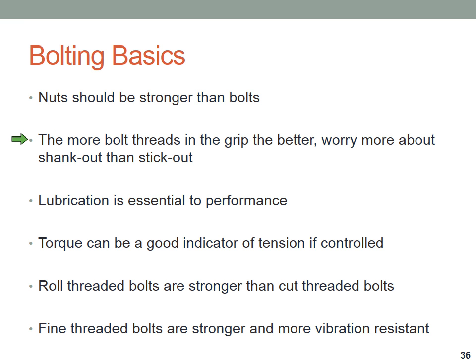Generally speaking, the more bolt threads there are in the grip, the better. Bolts are essentially very stiff springs. Most of the stretch that occurs in a bolt when it's under high tension is in the area of the highest stress, or the smallest diameter, which is in the threads. As a bolt is tensioned, most of that stretch is happening in the threads. If you haven't left very many threads within the grip, you're relying on that small number of threads to do an awful lot of elastic stretch, and sometimes they don't have the capacity.